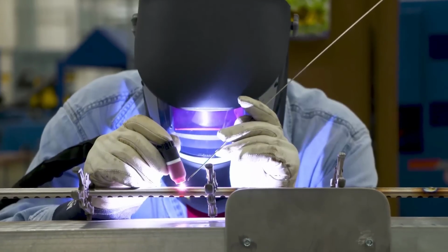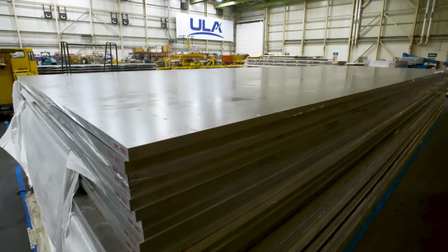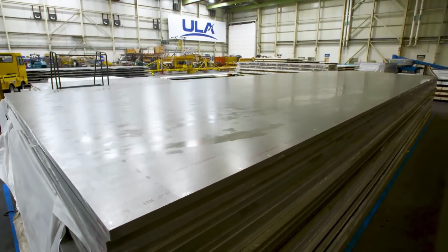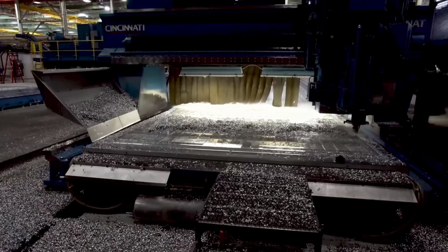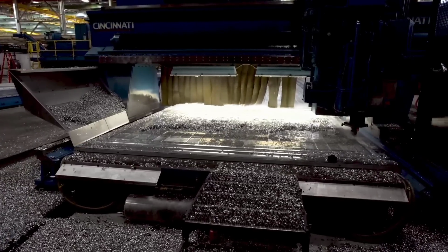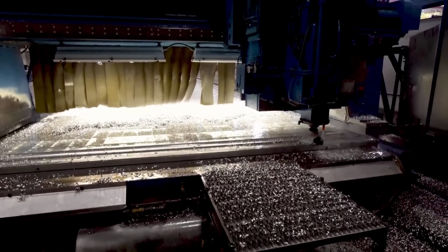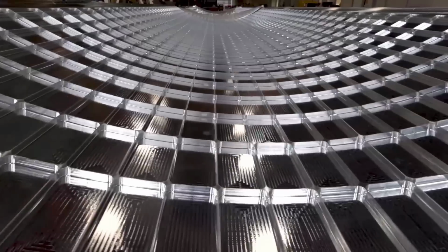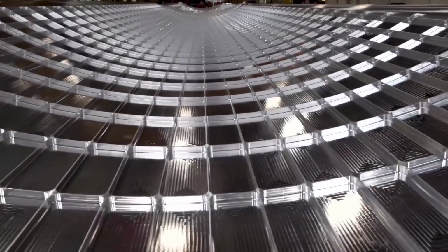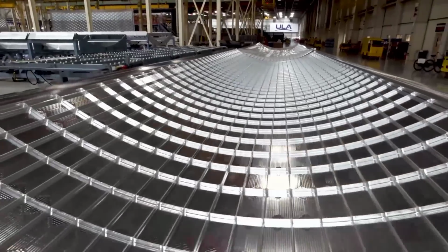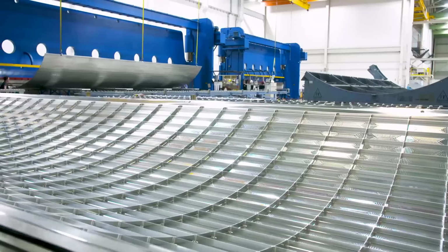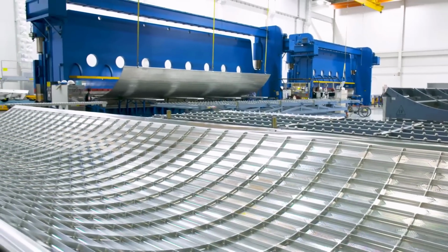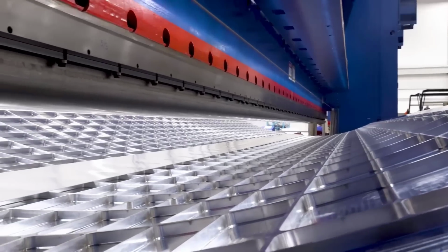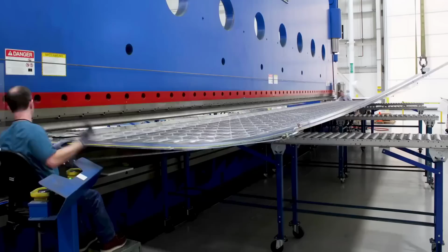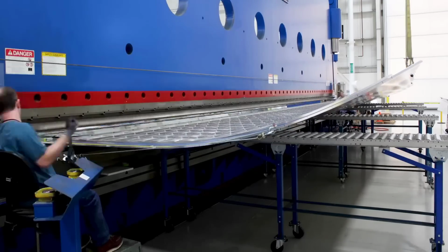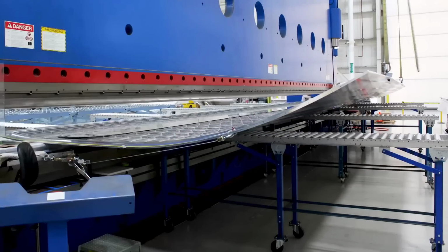At the heart of this manufacturing marvel lies a synchronized symphony of intricate processes and cutting-edge technologies. The production commences with the transformation of large aluminum plates into designed patterns through a series of 4 double gantry skin milling machines. This initial step not only shapes the components, but also significantly reduces their weight by a staggering 70%, while preserving around 75% of the original material strength.